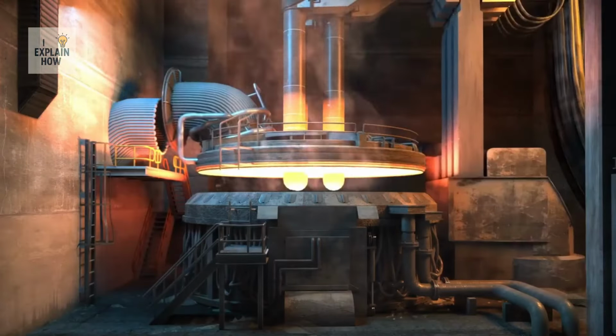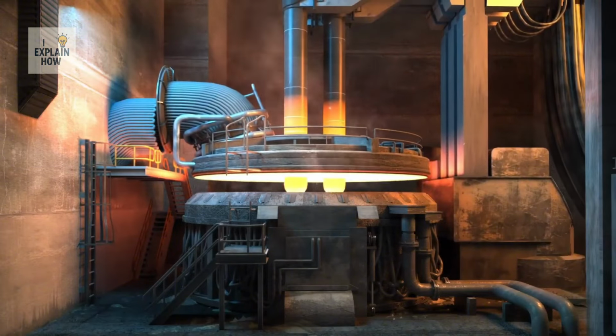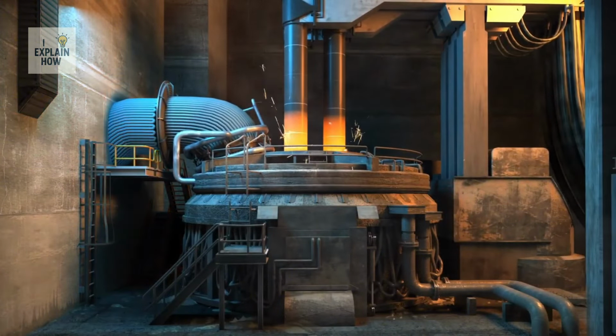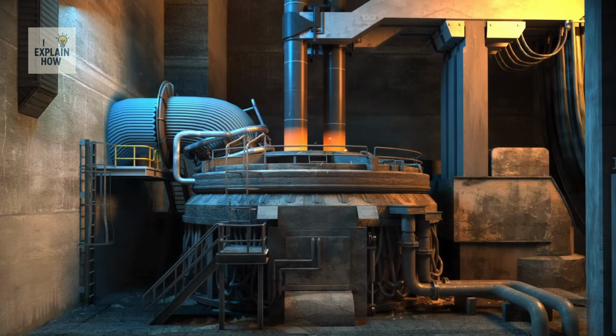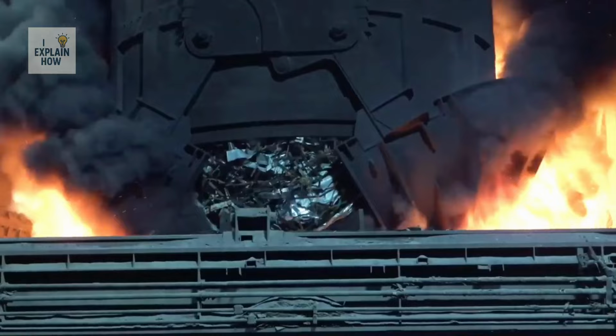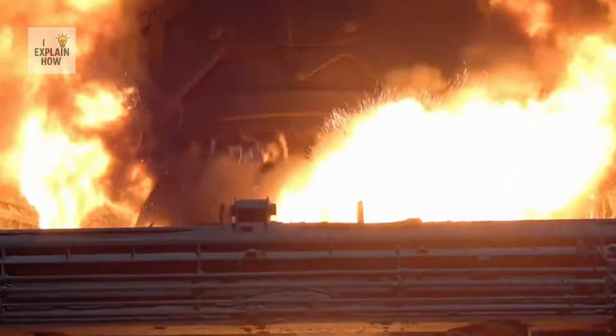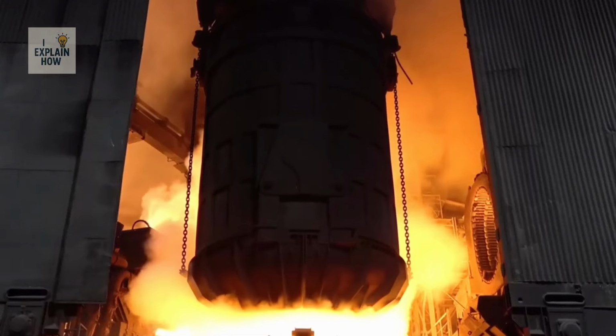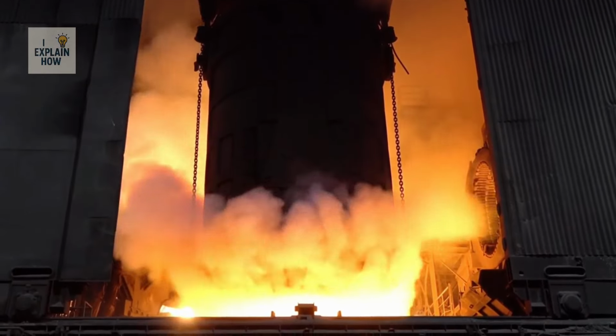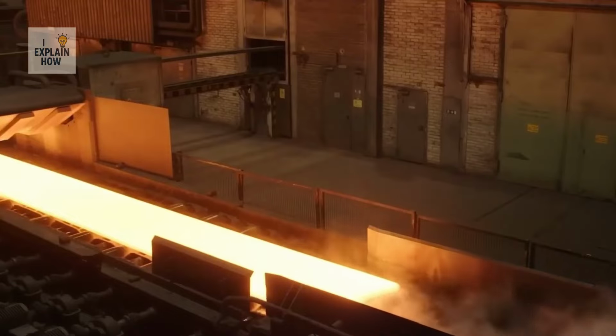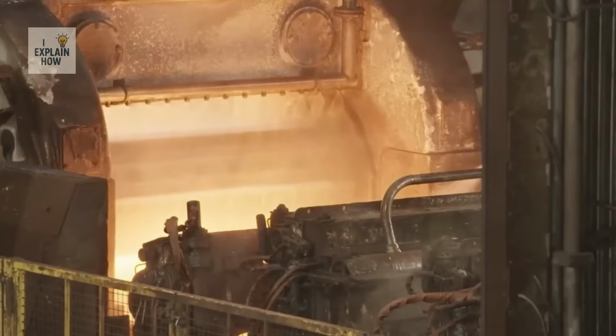These blocks are sent to an electric arc furnace. There, they face infernal heat. Graphite electrodes release currents of tens of thousands of amperes, generating an arc similar to artificial lightning. Within minutes, the temperature climbs to over 1,600 degrees Celsius, transforming the steel into melted steel.